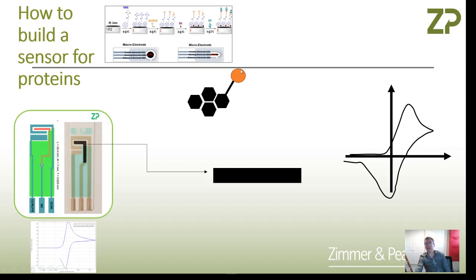And on the other end of the molecule, there's what's called succinimide. And succinimide is a coupling agent that we can use later on to couple an antibody. So what we do is we take these pyrene and the succinimide, they're covalently bonded together, and we basically functionalize the surface. So the carbon is no longer a carbon surface. It's a carbon surface with these coupling agents protruding from the surface.